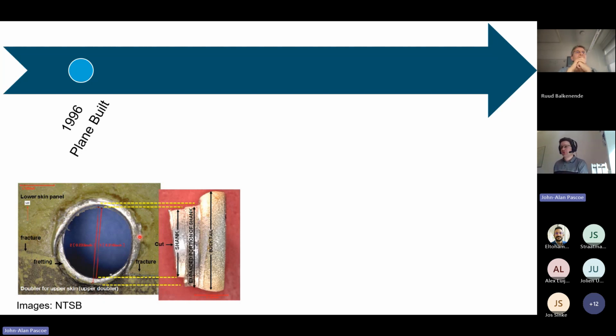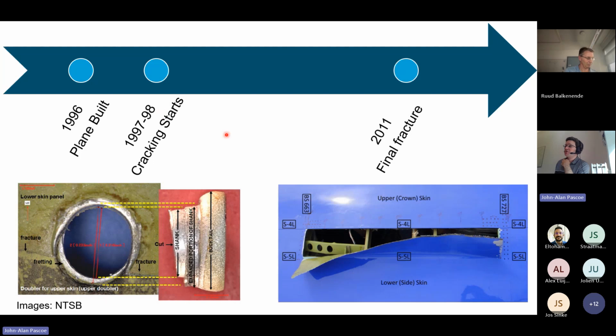The stresses were not distributed correctly, and so very soon, about a year or so after the plane was built, the material started to crack due to these increased stresses. Right? We have a phenomenon called fatigue. So if we have repeated loading on a piece of material, that can start to damage, and that damage grows over time. It's quite a slow process because it took another 12 years, 13 years before finally the crack got large enough that the remaining material could no longer carry the loads, and this entire piece of fuselage just unzipped and let out all the air.